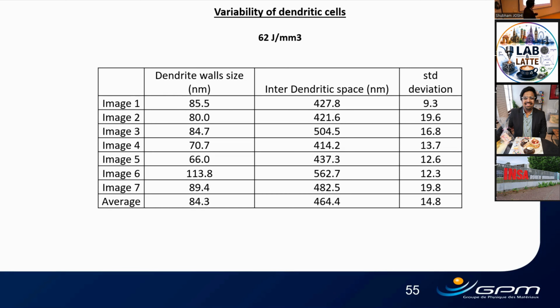About the first question, yes, we analyzed dendrite wall size for 7 different locations, as I mentioned. Oh, I mentioned 8, sorry, for 7. So yes, we have variability in terms of cell size and wall size. First, we were going for this wall size modeling. Anyway, there is a modeling based on, let's say, GNDs, or focused on hard zones. So we were thinking to go for the dendrite wall size, because we can compare the fraction of the dendrite wall and try to analyze it with the hard zones. But finally, we decided to go with the soft zone dislocation analysis, and that's the reason we could eliminate the dendrite wall size. But certainly, it is an influential parameter.